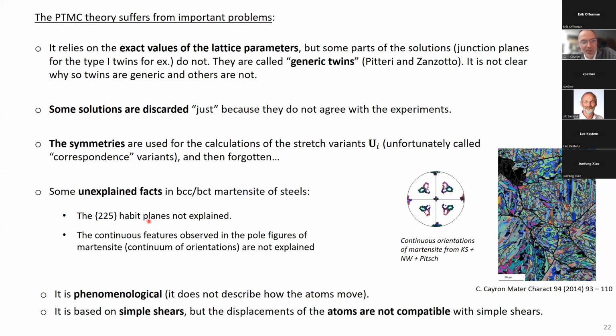For example, the {225} habit planes in steels is not explained by the theory. And also, if you do EBSD on martensite, you realize that actually it's not a unique orientation. Martensite is often made of a gradient of orientation. And in the pole figure, for example, we see some continuum of orientation inside, and this is not explained by the PTMC. The other point is that it is phenomenological because it does not describe how the atoms move. And to me, the problem is that it is based on simple shear, and simple shear is not compatible with the atoms.